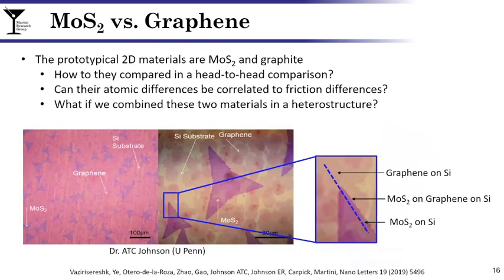To take this one step further, we did a study comparing MoS2 and graphene, or graphite. The 2 prototypical 2-dimensional materials are MoS2 and graphite, and these indeed are the ones that are used in practical applications today. What we wanted to do was a head-to-head comparison such that we could differentiate between their frictional behavior and correlate that to differences in their fundamental structure. This study was made possible by samples that were synthesized in Charlie Johnson's group at the University of Pennsylvania. What you're looking at on the left are optical images of these samples, and what you can see is that they deposited both graphene and MoS2 on a silicon substrate.